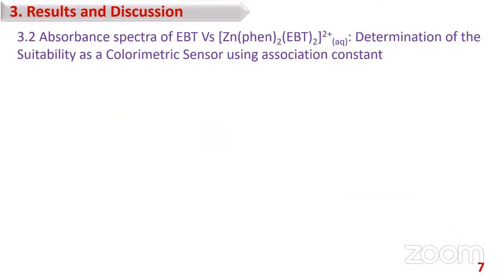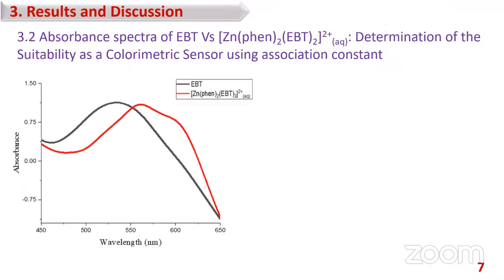Let me move on to the next slide to determine the suitability of zinc phenanthroline EBT complex as a colorimetric sensor. This is the graph showing the absorbance spectrum of EBT in black color line. The band maxima at 546 nanometer of EBT spectrum gradually redshifted to 565 nanometer upon the addition of the zinc phenanthroline complex. And simultaneously, a new band appeared at 600 nanometer. Those two new bands correlate the binding of the zinc phenanthroline to EBT. This spectral change shows its suitability as a colorimetric sensor.